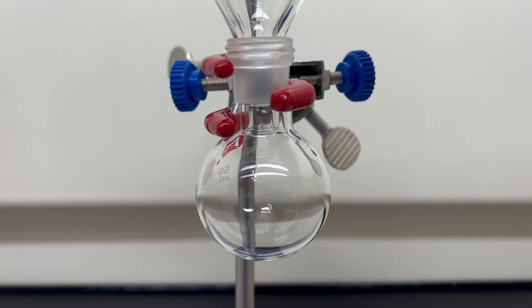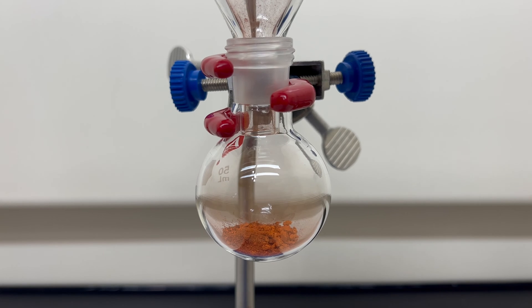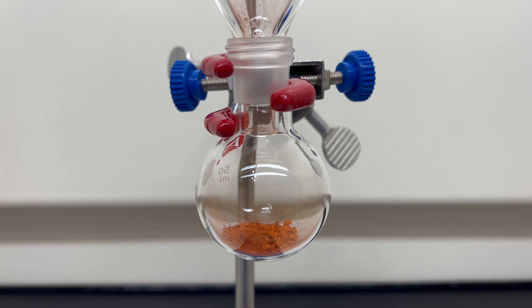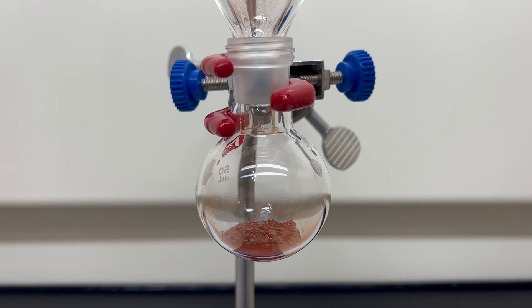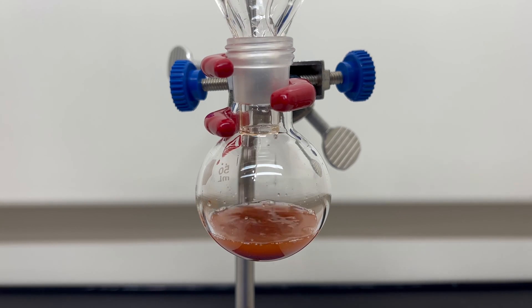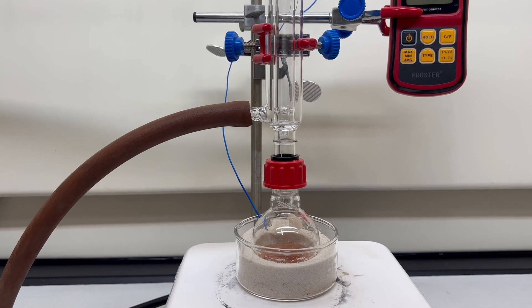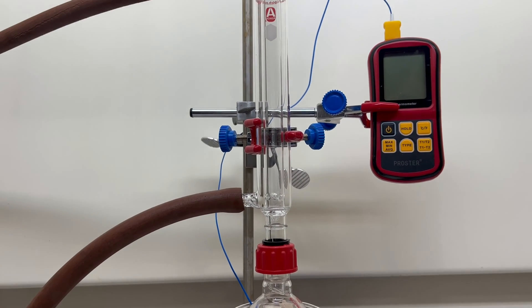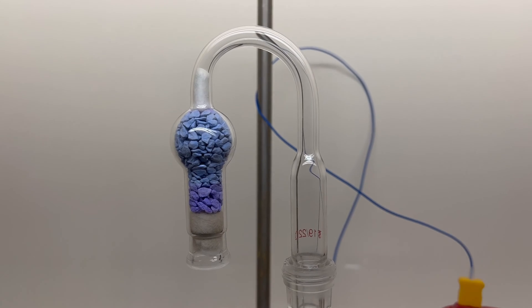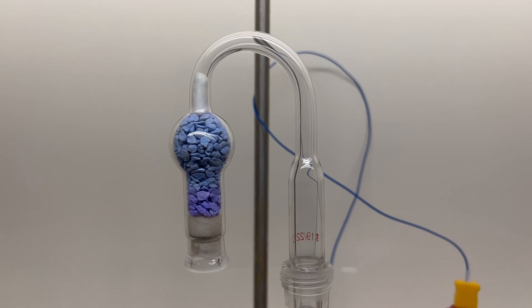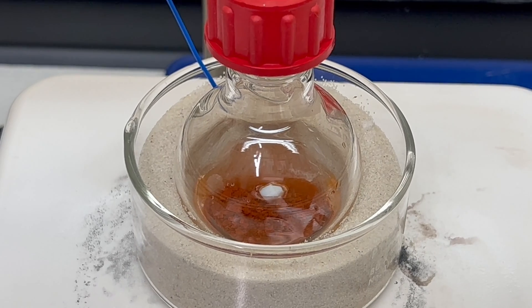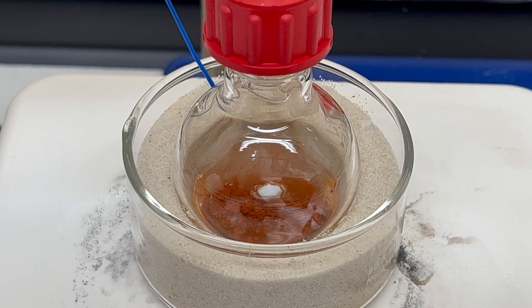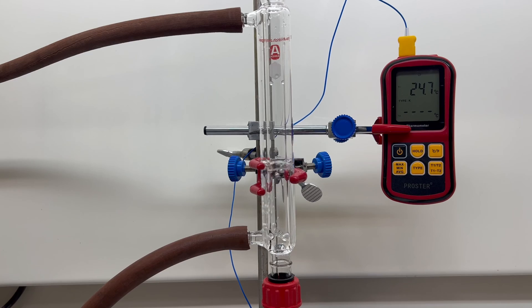We begin with 4 grams of uranium trioxide and add that to a 50 milliliter flask along with a stir bar. Next, 10 milliliters, 17.1 grams of hexachloropropene is added. A reflux condenser is then connected to the reaction flask. A drying tube is then connected to the condenser. The flask is then lowered into a sand bath on a hot plate. Cooling is started along with stirring.